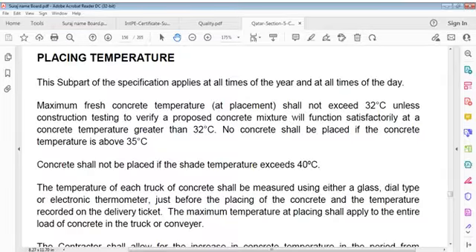It says maximum fresh concrete temperature at placement shall not exceed 32 degrees Celsius, and this is for whole year, all times of day. Unless construction testing verifies a proposed concrete mixture will function satisfactorily at a concrete temperature greater than 32 degrees Celsius, no concrete shall be placed if concrete temperature is above 35 degrees Celsius. And if shade temperature exceeds 40 degrees Celsius, no concrete shall be placed.